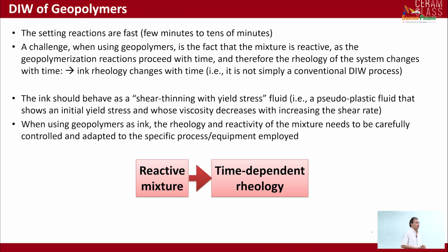So you already know what direct ink writing is. In the case of geopolymers, you have to realize that the setting reactions are quite fast, and this poses a challenge because it is a reactive mixture with a time-dependent rheology. So when we print, for instance, we print surrounding the syringe with ice in order to keep the temperature down and allow for a printing window that can be up to 3 hours. And the ink should behave as a shear thinning yield stress fluid.